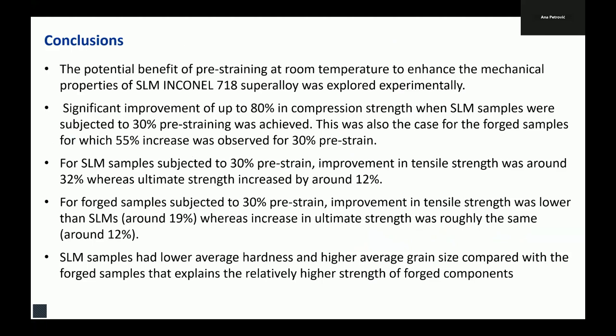There are some cases where the changes or the impact is very significant, and there are cases that the impact is not so significant. For example, I can stress on this one, significant improvement of up to 80% in compression strength when SLM samples were subjected to 30% pre-straining was achieved, which is very significant, very important. It is very promising that pre-straining could be used as a post-fabrication process to significantly improve the mechanical strength of Inconel, where we use the SLM technique to make them.